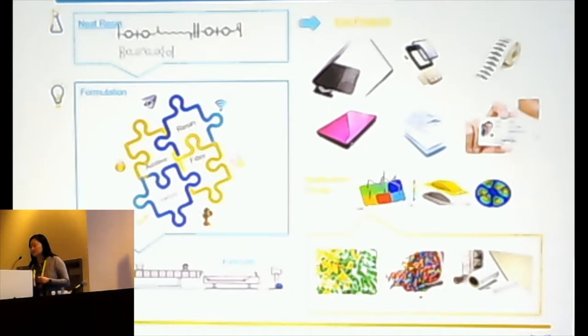So we have to make neat resin, but we normally don't sell the neat resin. We try to come up with differentiated solutions based upon the resin we have. There goes the formulation side. The formulation here is not necessarily limited to the compounding process. We can also try different techniques to combine the resin, filler, additive, and interfaces, to play with the interfaces to achieve our goals. And you can see here, there's an extruder here.